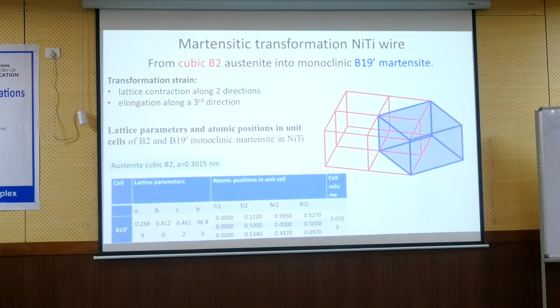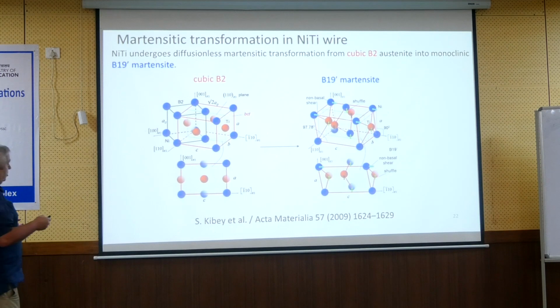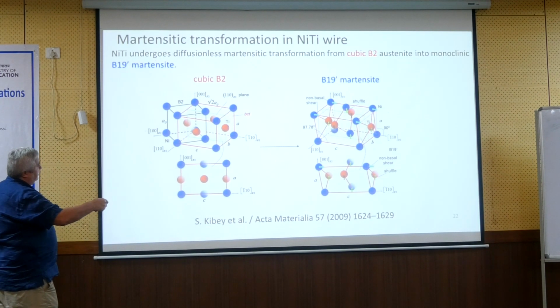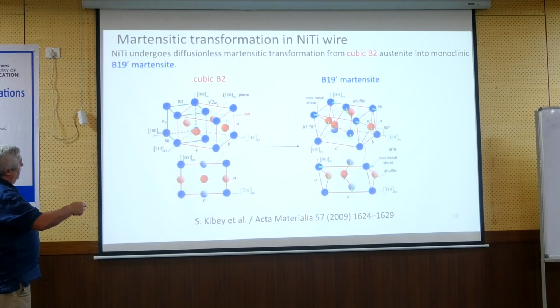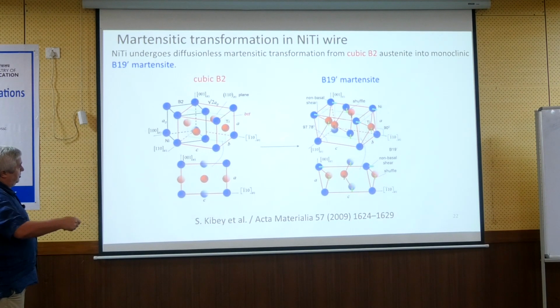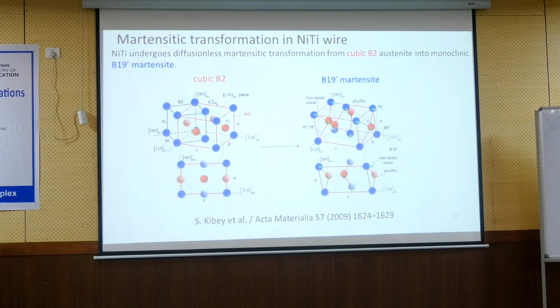And this is only the shape of the lattice, but in fact the lattice is made by atoms, so you have to know the position of the atoms. Here this is the austenite with nickel and titanium atoms. Titanium is in red, nickel in blue, and this is how it's converted into the martensite. This is the animation you have seen before, and this is the projection, but now you see the position of the atoms. The exact position of the atoms is not so easy to imagine only from this shape strain. You have to take into account some other deformation to really obtain the structure with atoms in the positions where they should be.